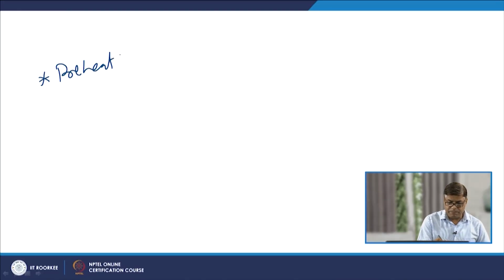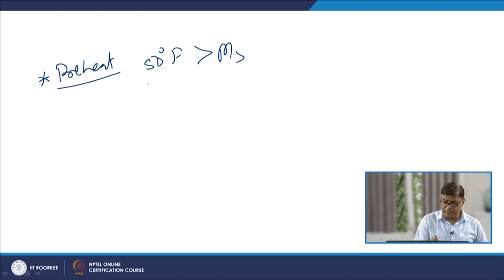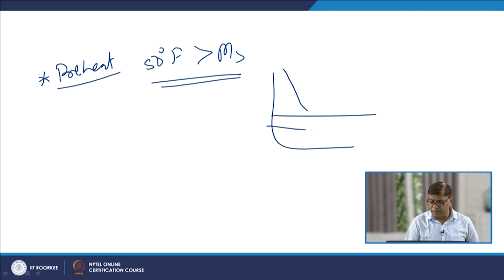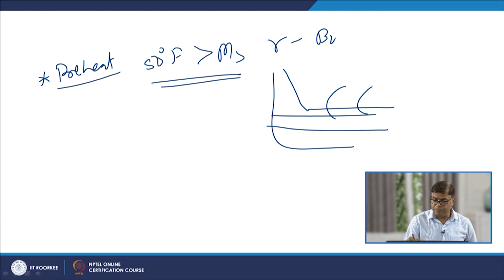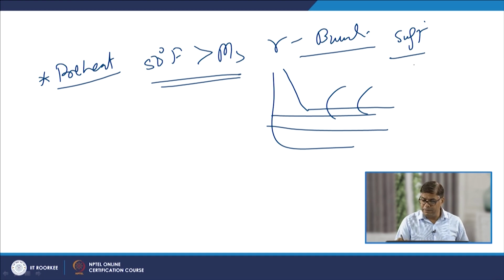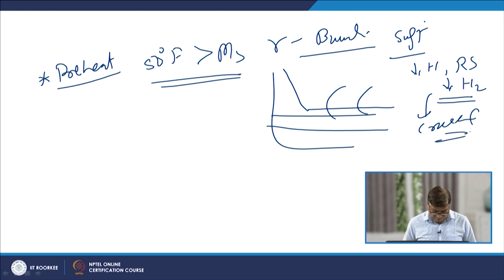So, like the one case we will take up, if the preheat temperature which is possible and being used is greater than about 50° Fahrenheit above the martensite start transformation temperature, then we know that since this is above the martensite transformation start temperature, it will be facilitating the complete austenite to bainite formation. Bainite being comparatively softer than the martensite, it will be reducing the hardness, reducing the residual stresses, reducing the hydrogen content in the weld metal. So, it will be simply decreasing the cracking tendency.